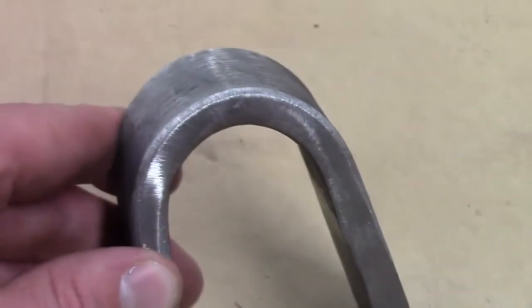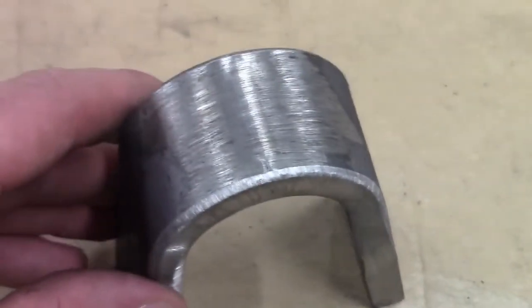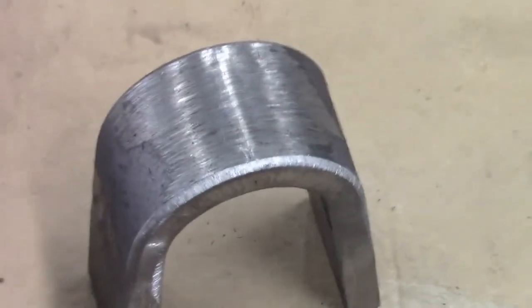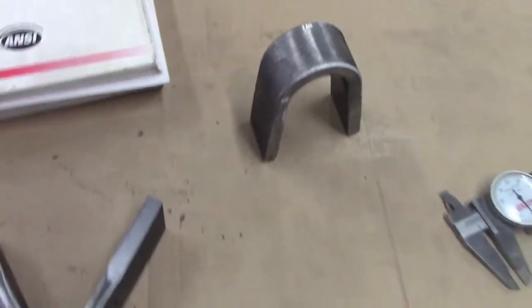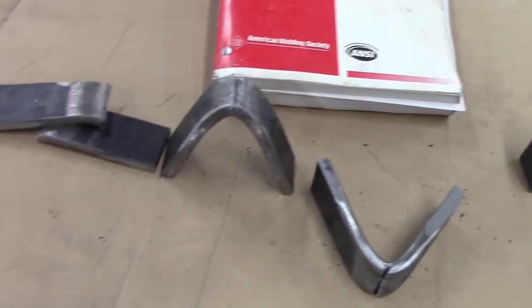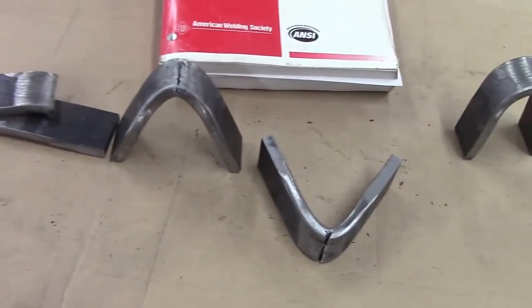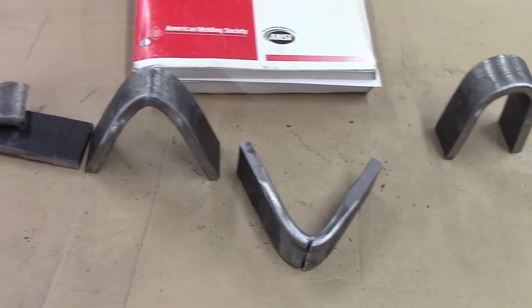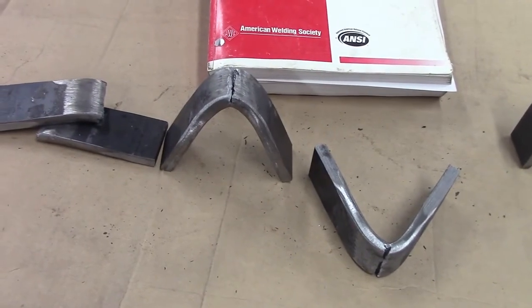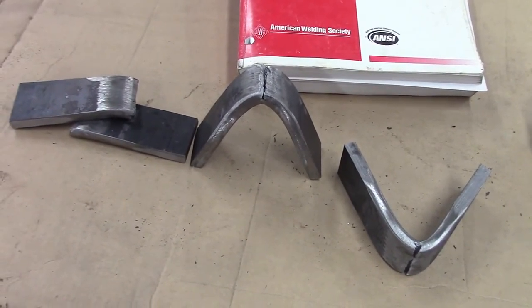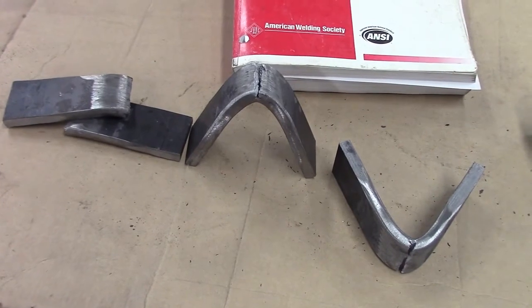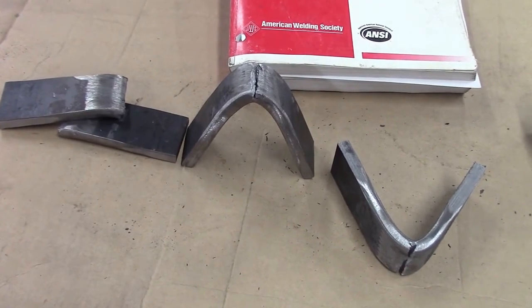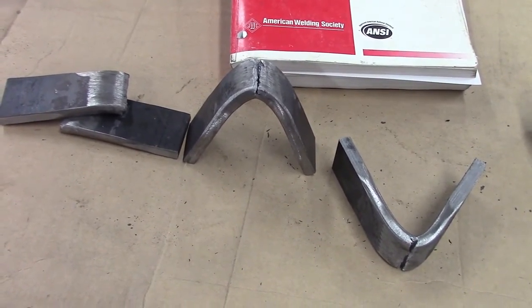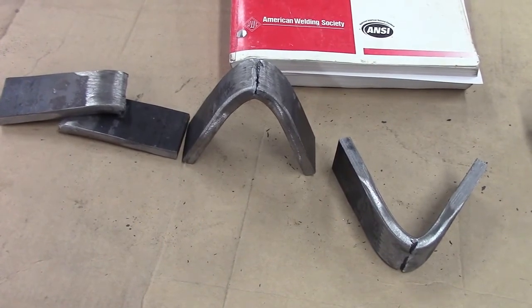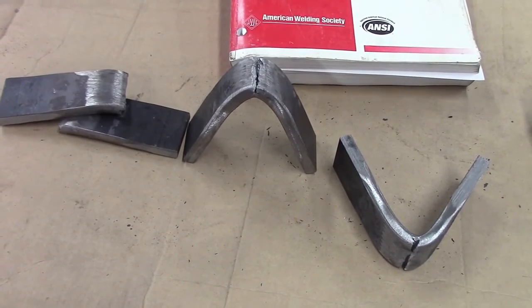So now if you were going to go and retest for this, what you'd want to do is increase your heat, because by looking at all these, why would one pass and the other 3 not? You got to change some of your variables in your welding procedures. Increase your heat. That means turn your wire feed up, turn your voltage up so that it blends in better and you get fusion all the way through your weld.